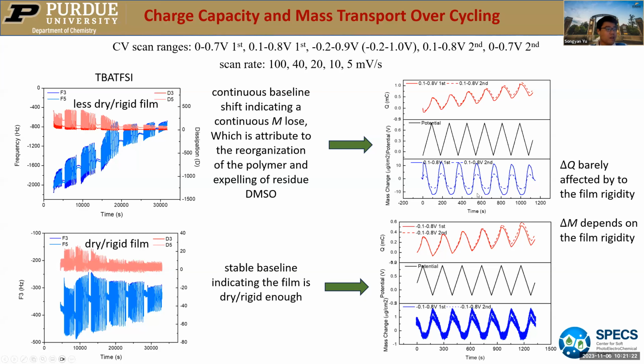Because when we have a less dry film, by cycling we make the film become more and more rigid, and we get a smaller mass transport during CV than before. Whereas with a very dry film, the mass transport several hours before and several hours later are the same. It's interesting because for many polymers we worry about ion trapping: during electrochemical cycling, ions and solvent accumulate into the polymer and cause mechanical failure of the film. In n-PBDF, however, we just see the polymer become more and more rigid.